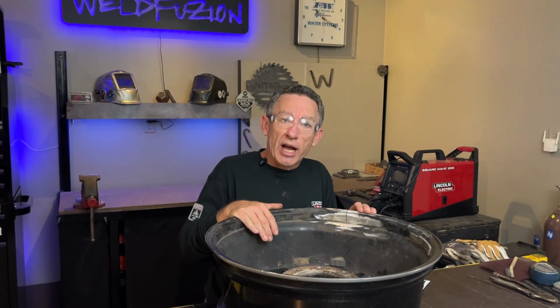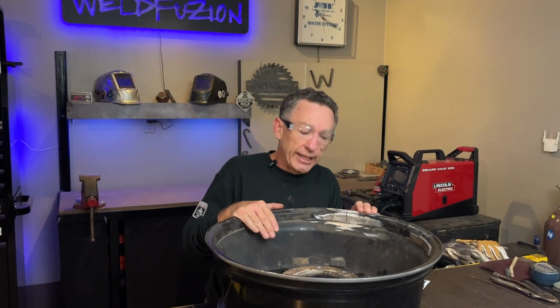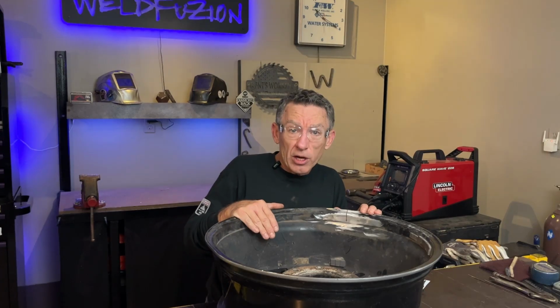We're at the stage now where you may be considering some preheat to burn some of that crud out of there and to get the puddle to flow a little bit easier. So let's talk about preheating aluminum. So aluminum's not like steel. Steel we can pretty much heat up to a few hundred degrees and not have to worry about anything happening until you get to that critical temperature above 1,000 degrees, right? Or somewhere in that ballpark. But aluminum melts at about 1,000 degrees. So it's a whole different animal.